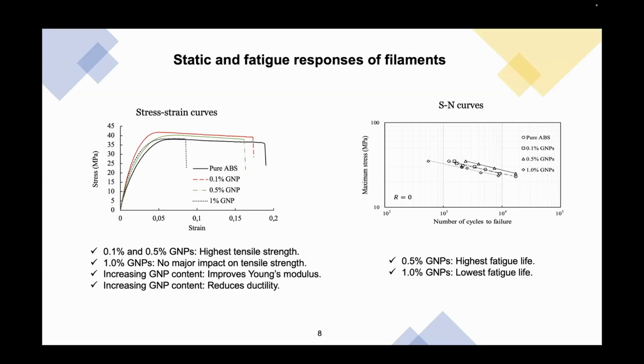Here we can see the results of stress strain curves and also the SN curves. We can see that adding 0.1 and 0.5% GNP can give us the highest tensile strength, while adding 1% GNPs, we can see that there is no major impact on tensile strength. From this stress strain curve, we will be able to find Ramberg-Osgood parameters. And then for the SN curve, we can see that adding 0.5% GNP can give us the highest fatigue life, and adding 1% GNP, the lowest fatigue life. Using those data for SN curve, we can determine the strain-based fatigue parameters.